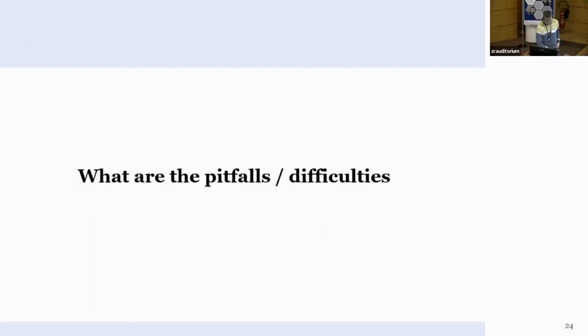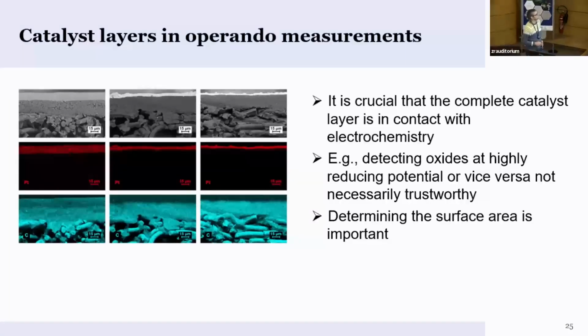So one, that was kind of what you can do, but there are many pitfalls and difficulties where we need some improvement of the techniques. So basically in the TEM, you look at a very thin catalyst layer, but in these operando measurements, you need enough material, and you look at real catalyst layers, so 3D layers, as they are also employed in a system. So you have a few micron thick catalyst layer,